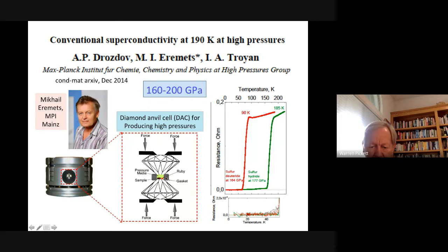There is a metal gasket here, which is deformed by the diamonds as they squeeze together, seals up the edges here, and then their sample is in here, and then there's a little piece of ruby whose vibration, one of its vibrations, is monitored in the experiment, because that's very well established how that frequency behaves with pressure. So that's the pressure measurement.